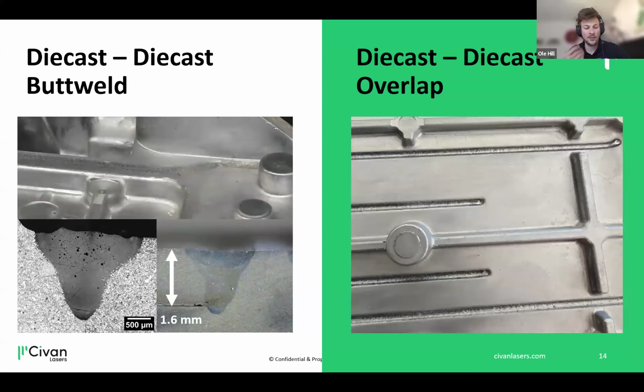where we intentionally don't create a keyhole. We just remelt the surface to make it very flat, and you can see it in this etching as well. It's just a small, let's say, half moon in the top 0.3 millimeters. It's just to reduce the surface porosity and also make it less likely for any pores to cause a leakage. It also results in a very nice looking surface finish, which is a little bit shiny and also has these repetitive patterns that you might recognize from manual welding.